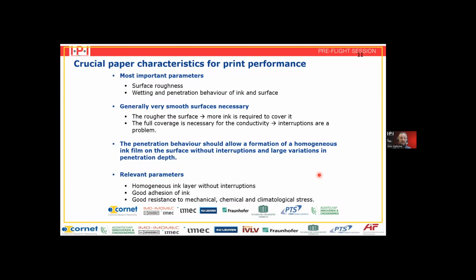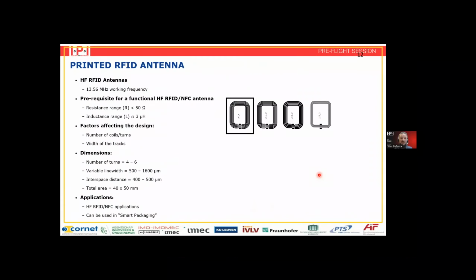analyzed in the project. If you look at the print performance, of course, the surface roughness and the wetting and penetration of the ink is very crucial. Generally, they say that you need very smooth surfaces, and a lot of applications or solutions use a coating on top of the fiber-based substrate and then deposit the ink. And of course, in view of going to low-cost applications, we tried to compare and to see if it could be done without this extra coating. So that's something that we investigated.